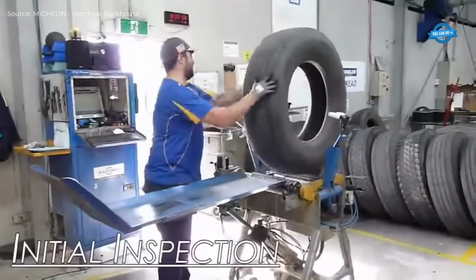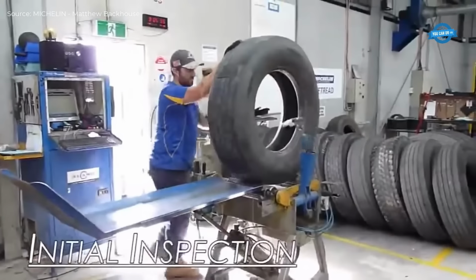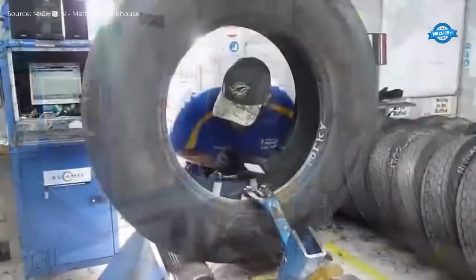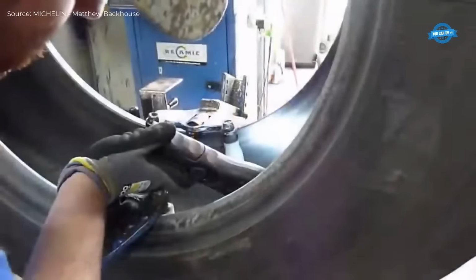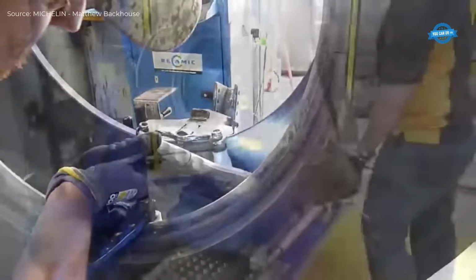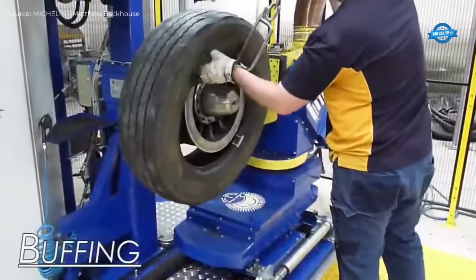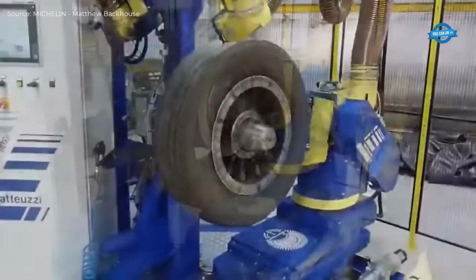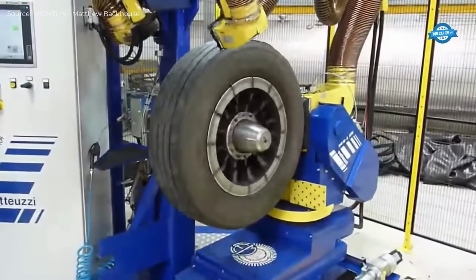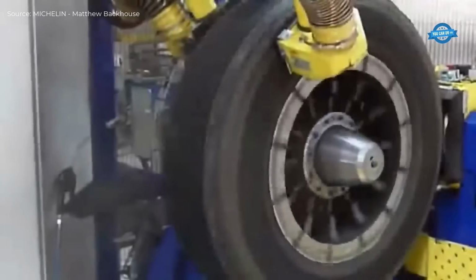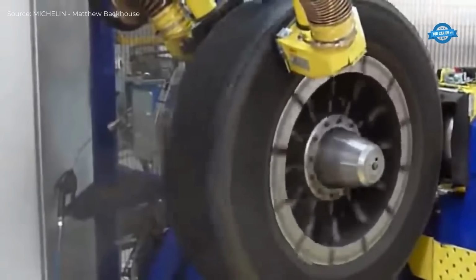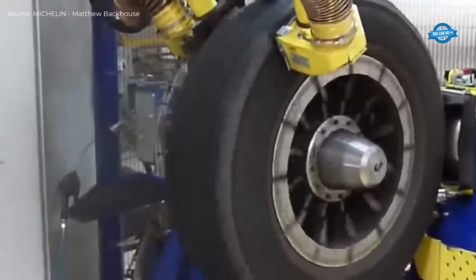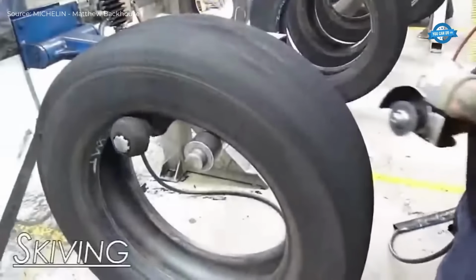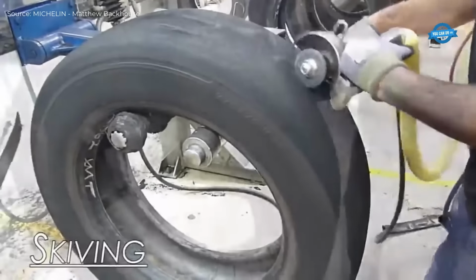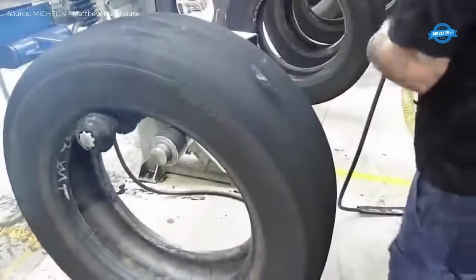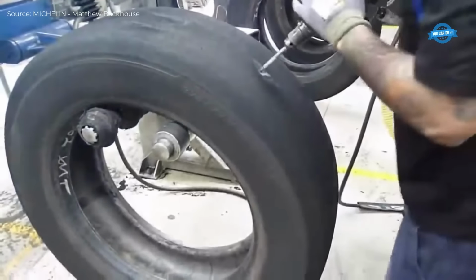Michelin retreading process. The process starts with a detailed inspection of the used tire casing to determine if it is suitable for retreading. The worn tire tread is removed using high-speed buffing machines, ensuring a consistent surface. The buffing process typically removes 3 to 5 millimeters of rubber while maintaining the correct profile for the new tread application. Technicians manually skive out damaged rubber sections that the buffing process cannot remove. This precise step prevents future failures.